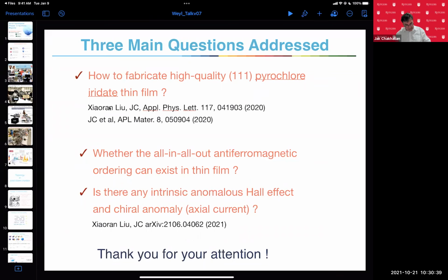However, what we found really peculiar, with the advantage of in situ growth and the ability to measure electronic structure with ARPES, is that we look at some of the surfaces which I didn't believe should survive more than several hours. In reality, we still could see the Fermi edge, maybe not the band structure because that disappears fast, but even the Fermi edge for more than a day and a half before we lose the surface.